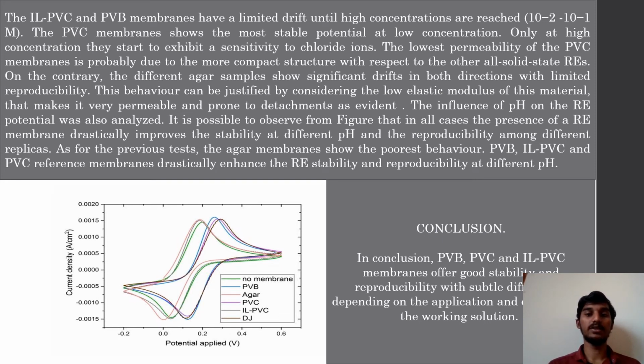The lowest permeability of PVC membrane is probably due to the more compact structure with respect to the other solid state REs. On the contrary, the different agar samples show significant drifts in both directions, which limits reproducibility. This behavior can be justified by considering the low elastic modulus of this material that makes it very permeable and prone to detachments, as evident.